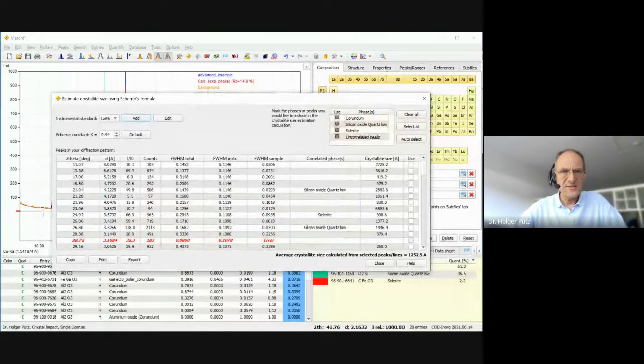And as you now see, something has changed. I am no longer asked if I would like to add a standard, because the standard is already present here at the bottom. And now we have a list of all the peaks, the total width that has been determined from my sample, the instrumental peak width from the standard, and the difference. And now the program can calculate or estimate the crystallite size from this sample width using the Scherrer formula and give the result of the calculation here below.